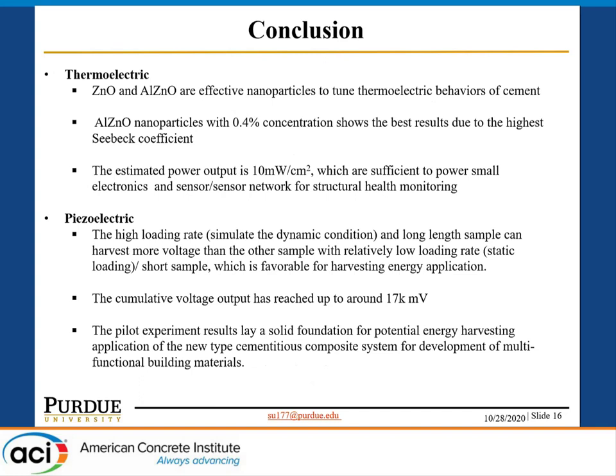So to conclude our work, for the thermoelectric part, zinc oxide and aluminum-doped zinc oxide are efficient nanoparticles to tune the thermoelectric behavior of the cementitious material. The aluminum-doped zinc oxide nanoparticle with 0.4 concentration shows the best result due to the highest Seebeck coefficient. The estimated power output we got is 10 milliwatts per square centimeter, which is good for powering small electronics. And for the piezoelectric part, our cumulative voltage can reach 17K millivolts, and it's favorable for multifunctional building material.